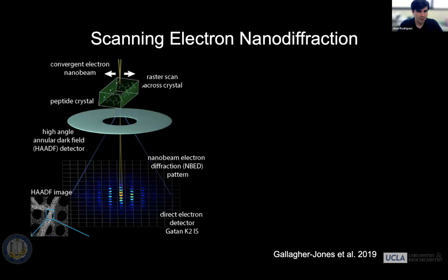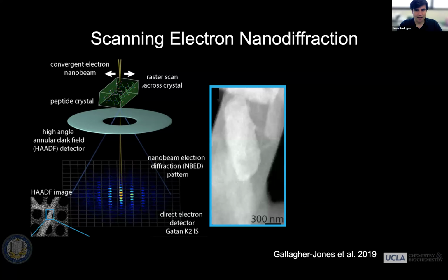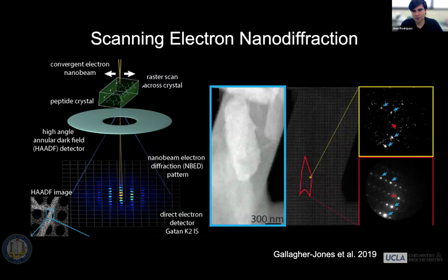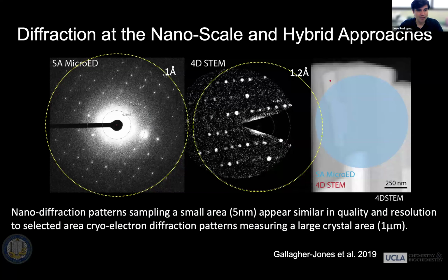This is, of course, the type of spatial mapping that is employed all the time in 4D STEM. And so normally you would get a HAADF image, which is the spatial mapping of signal within the field of view. At the same time, you're also getting diffraction patterns for each of the illuminated subregions in that field of view. And we're making use of those diffraction patterns. And just to show you a comparison of the type of selected area electron diffraction that we might get from some of these crystals, from a subregion of that crystal subtended by the blue circle on the right-hand side, that compares to the type of diffraction pattern we would get now from this small red dot, which is the illuminated area. This is a single 4D STEM pattern where you can see a very clear lattice, still indicative of a well-ordered diffraction from that one small 5 nanometer area of that crystal.